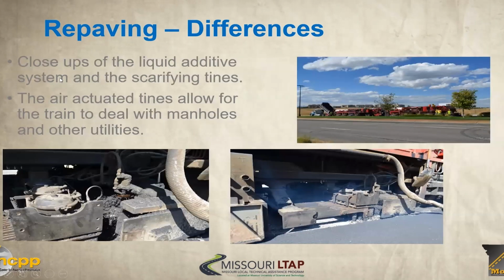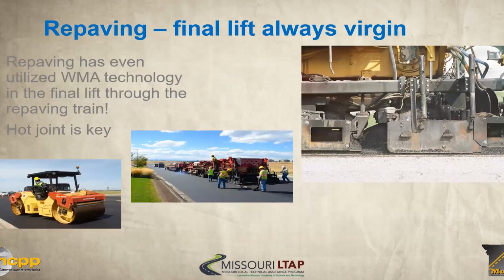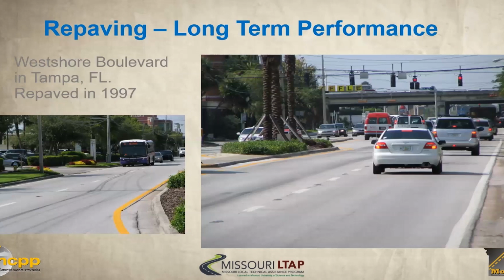As far as close-ups of the liquid additive system, you can see that right here. The rejuvenating agent is added. You can see the scarifier, and right over here there are the tines for the scarifiers. They're air actuated, so they'll pop up if they come in contact with a manhole or other utility. This is interesting because we're going to combine the first part with the second part, where warm mix technology has actually been used in the final lift through a recycling train. And here, as you would expect from the NCPP, I'm using an example from Florida. This is a recently taken picture of West Shore Boulevard, and this was repaved in 1997. So very good long-term results with these processes.